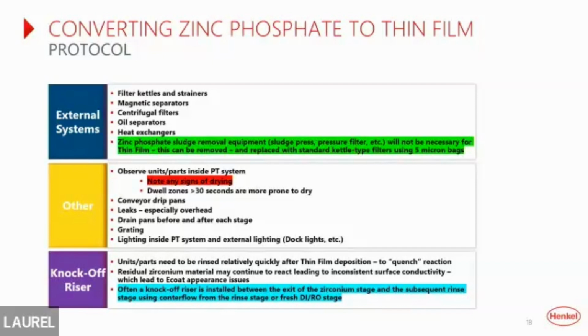A couple of things to note is zirconium process does not require those specialized sludge removal filters that zinc phosphate does. That's one of the huge advantages of zirconium. It doesn't produce sludge. Doesn't require those boil outs. So the first thing you can do if you want is ceremoniously just rip that sludge filter out that always seems to be clogging up or breaking down. What you want to do is just use standard filter kettles with filter bags. 5 micron is recommended. You can go a little bit higher if you need, or you can go down to 1 micron. So that's a huge benefit.